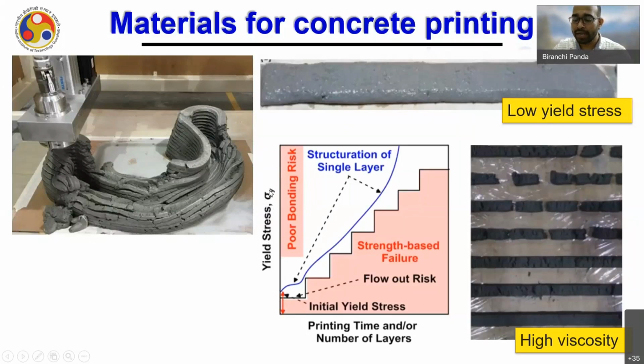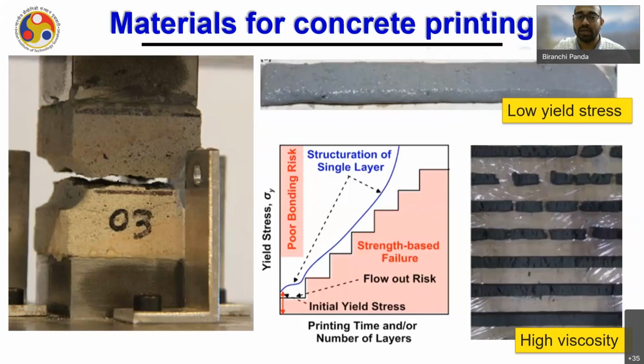If it is too high, then we are going to have a very poor interlayer bond strength. So what is going to happen if you do the bond test? You will get a very poor interface bond strength. So it means we need a minimum yield stress for printing, and with time the yield stress has to be increased. Otherwise, you cannot deposit more layers.